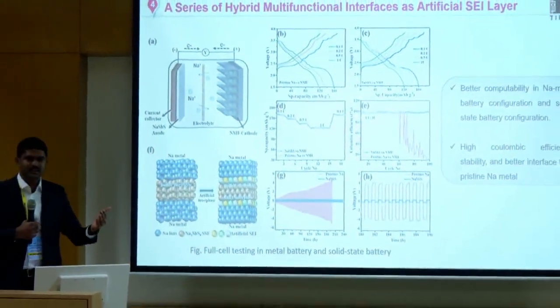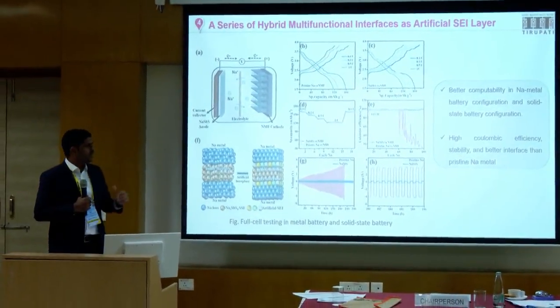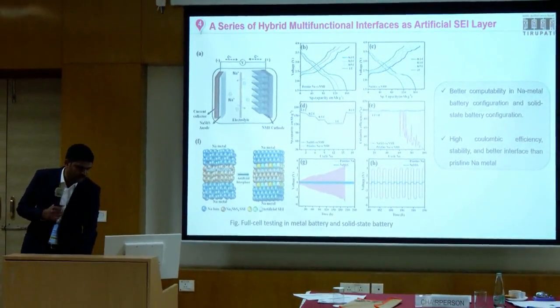We have successfully studied the batteries at a coin cell level prototype, and the batteries can be cycled at a current density of around 10 milliampere per centimeter square with a capacity of around 30 mAh per centimeter square efficiently. A significant leap from our previous study. And when we studied a practical cell, it can be a sodium metal based battery or a solid state battery, which are really fireproof or explosion proof. These batteries employing our modified sodium metal anode nicely showed good stability over several hundred cycles when compared to conventional sodium metal anodes without any natural SEI or artificial SEI layers.